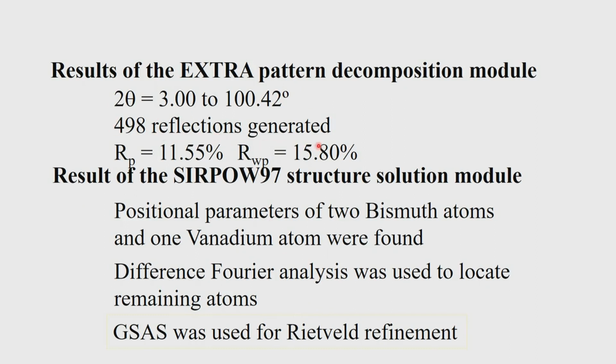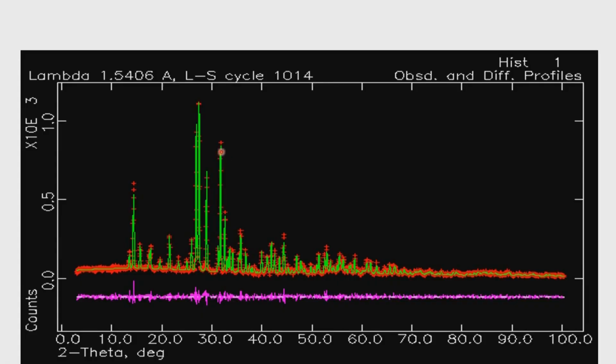The example given here is that with that we were able to isolate and identify 498 reflections. So, it is not just the peaks. If you count the number of peaks here, 1, 2, 3, 4, 5, 6, like that, maybe about 35 to 40 you will get. But if you do this analysis of where each and every HKL can come in this crystal system, once the pattern has been indexed and a, b, c, alpha, beta, gamma are known, we can calculate how many reflections will come up.